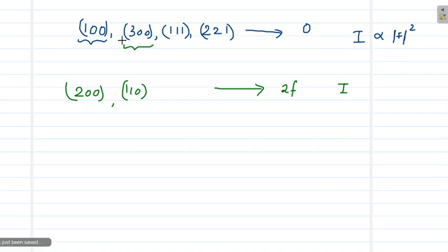This is because the alignment of planes is in such a way that the diffracted beam from one plane is cancelled by the next plane. For example, for the 100 plane, we have the 100 planes like this, and for the BCC lattice, the next layer of atoms comes here, and following that we have another layer.